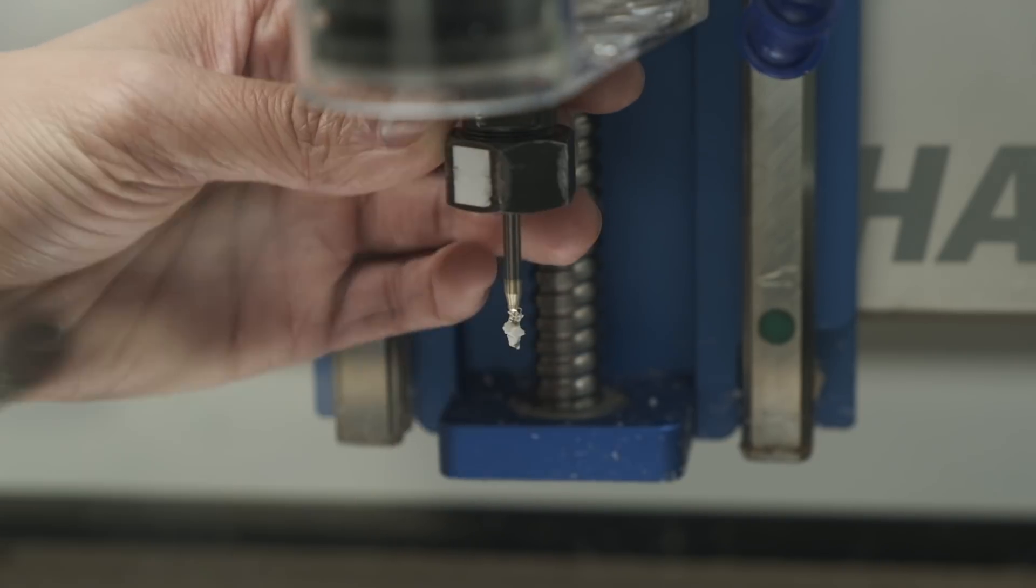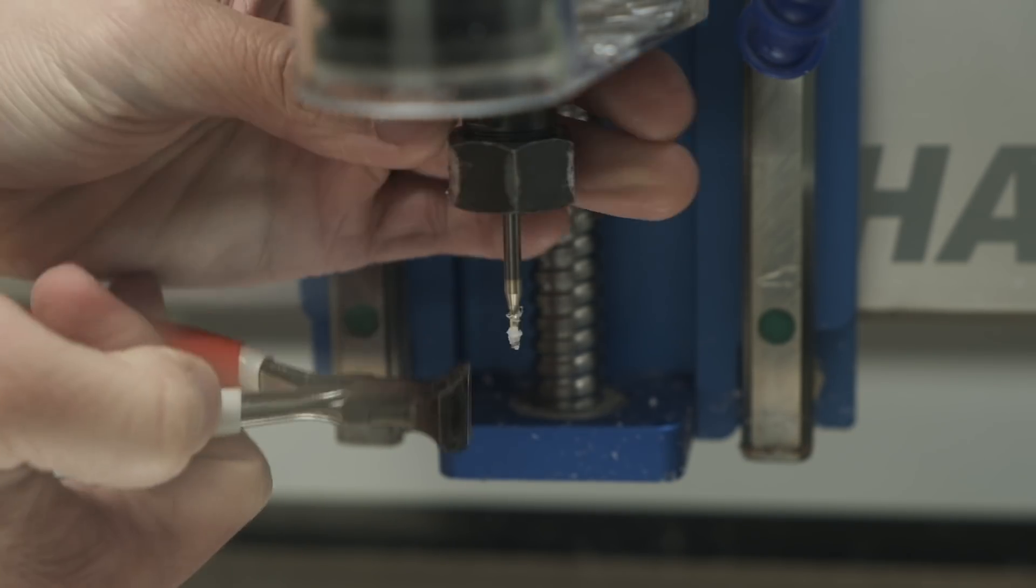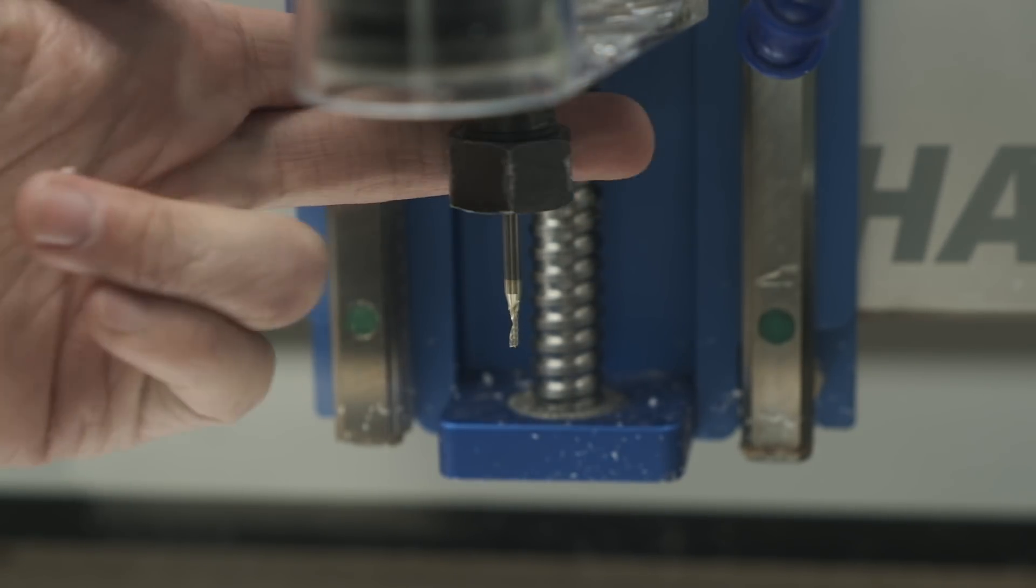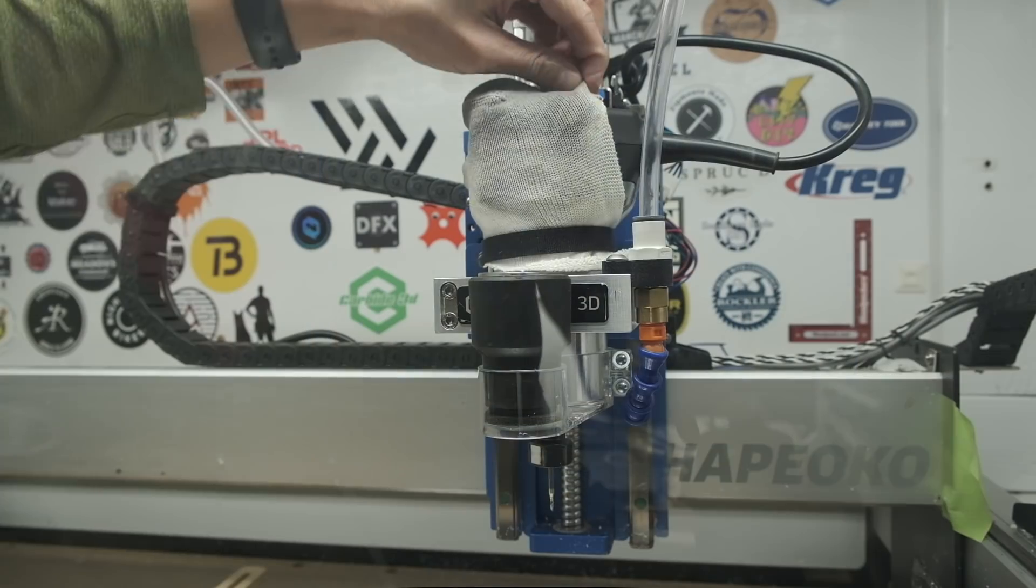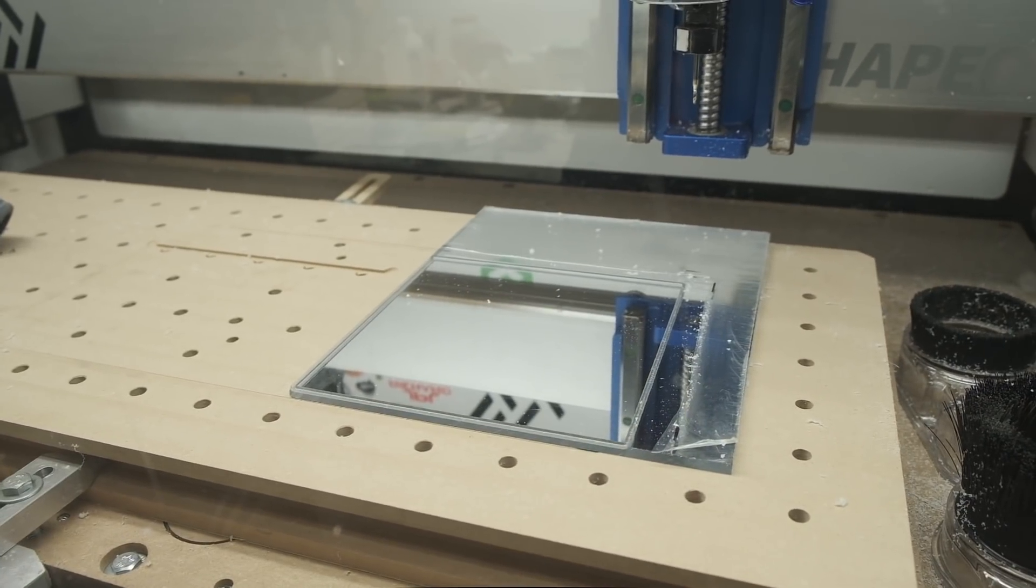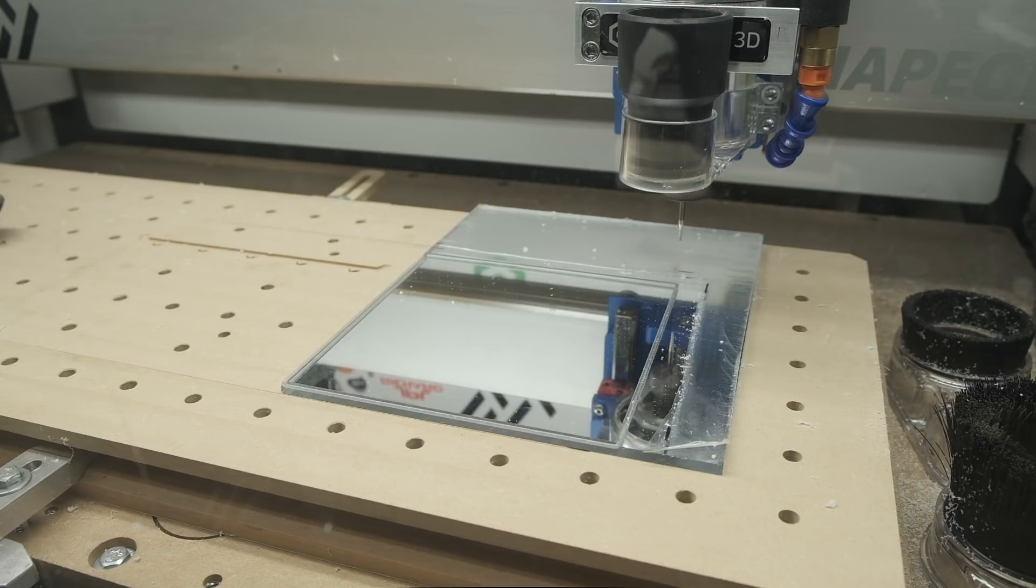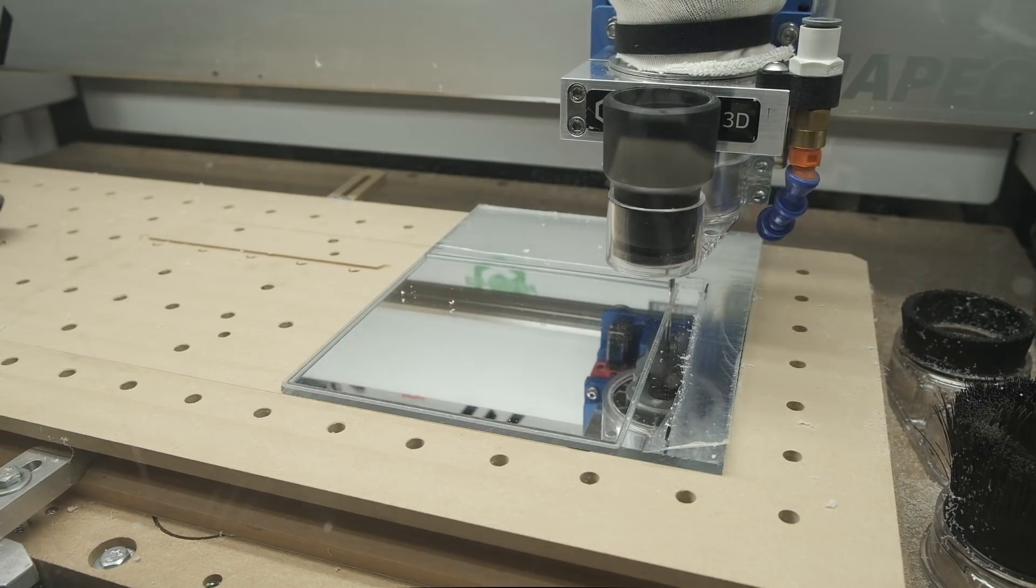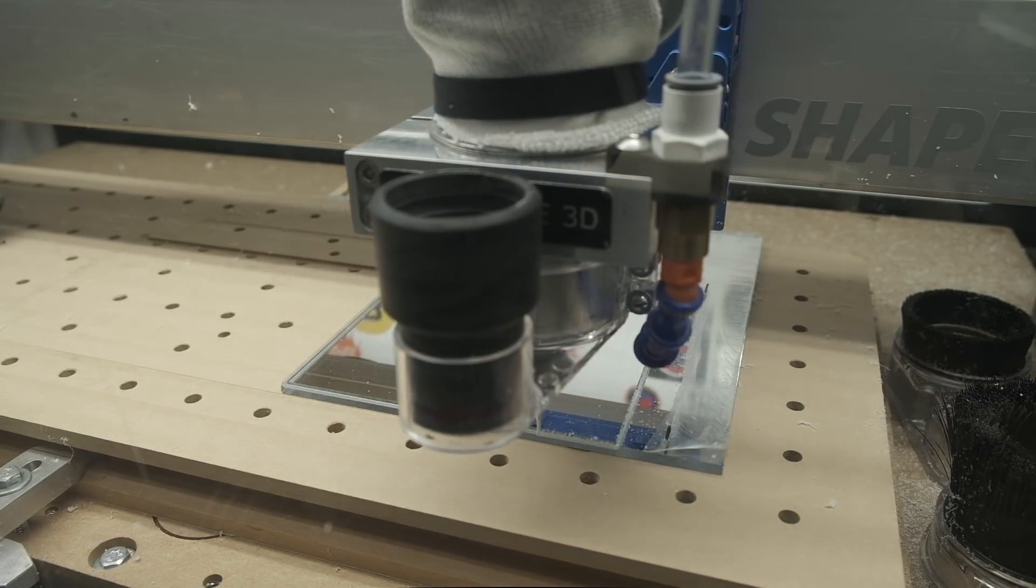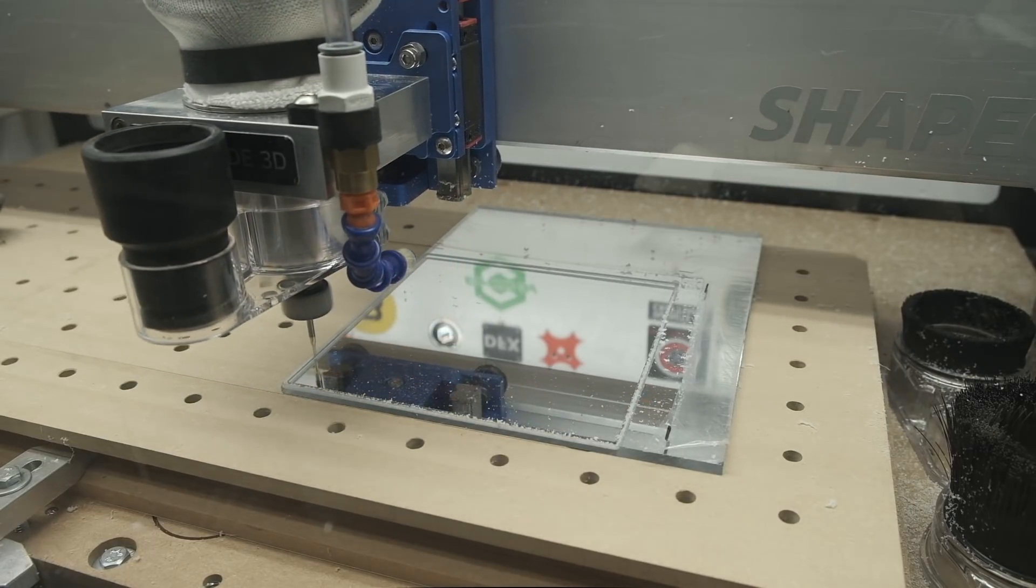You can usually be pretty rough with eighth inch or larger end mills, but this 2mm single flute is much more fragile. You have to be super conscious to never twist or push laterally on a tool like this, and even then, my success rate for clearing these up is only about 66%. I wasn't sure what was going wrong here since this was a recipe I'd used before. For 2mm and 16th inch end mills, I usually feel pretty safe around 16 to 18,000 RPM, but out of an abundance of caution, I backed the RPMs down to about 14,000 without adjusting the feed rate.